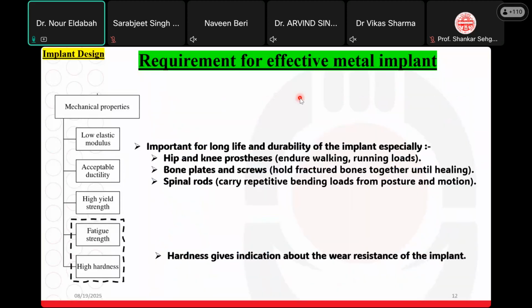Finally, there is the fatigue strength. For example, the knee joint is exposed to cyclic loading while moving, going upstairs or downstairs. So you should consider high fatigue strength of the alloy. Finally is the hardness, and the hardness gives us some indication about the wear resistance of the implant. Making it high hardness with low elastic modulus means that our implant has good wear resistance characteristics, and this is strongly required for metal implantation.